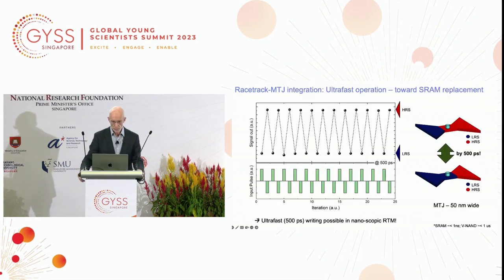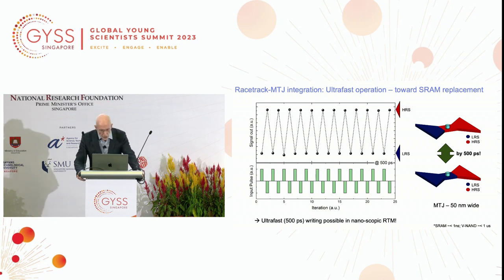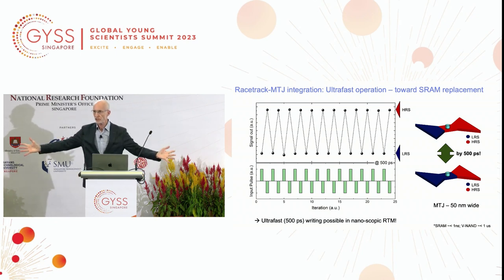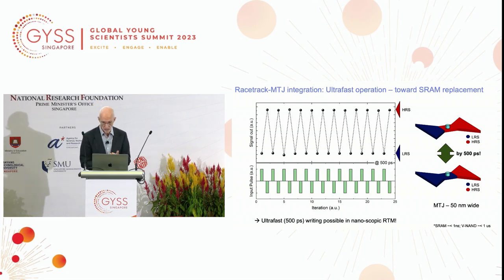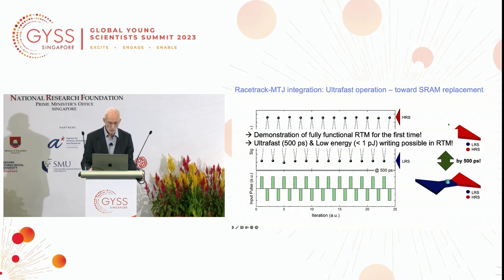Now, at Max Planck, since I came, we have with some funding from Samsung, we've shown we can go from micron-sized racetracks down to nanometer-sized racetracks. Turns out everything works exactly the same, same velocities, and we've now built, for example, a device where we have a single domain wall. We move it backwards and forwards and detect its position from an integrated magnetic tunnel junction, and we can do this on a time scale of less than 500 picoseconds, an extremely low energy. So we believe this is a very interesting single domain wall device, super high performance, which we could use to replace the densest memory today in charge-based world of electronics, which is called static random access memory.